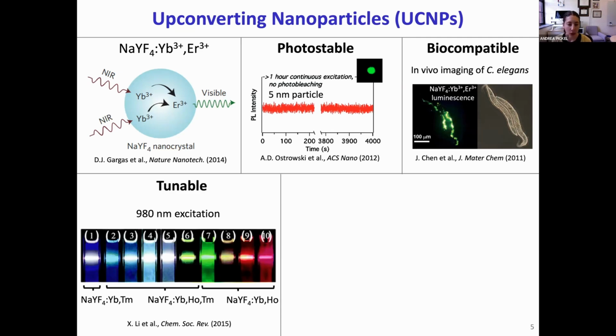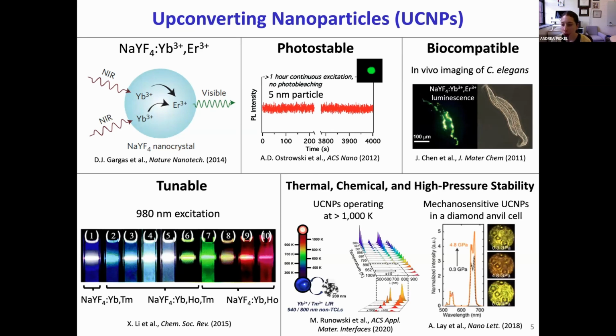UCNPs are also highly tunable, so just by swapping out one dopant for another or changing the dopant concentrations, you can get a big change in parameters like emission wavelength. And my group is also particularly interested in UCNPs because they have excellent thermal, chemical, and high pressure stability. So they can operate at temperatures over 1,000 Kelvin, for example, or under elevated pressures generated by a diamond anvil cell.